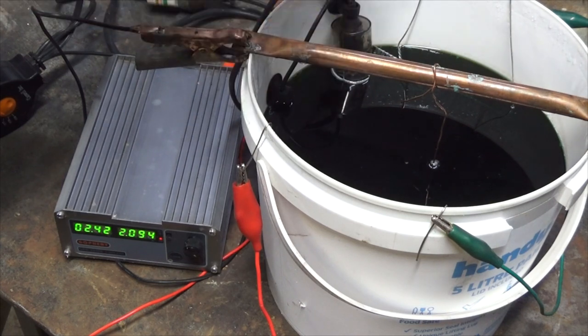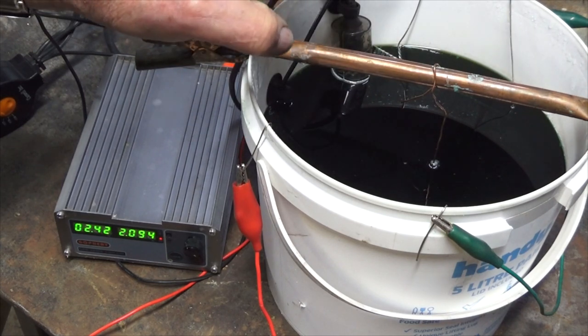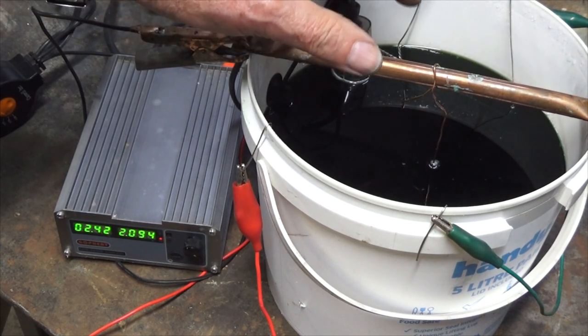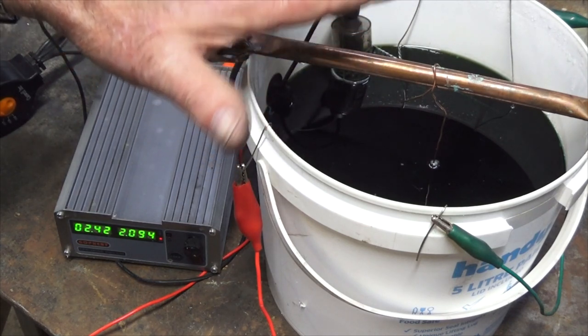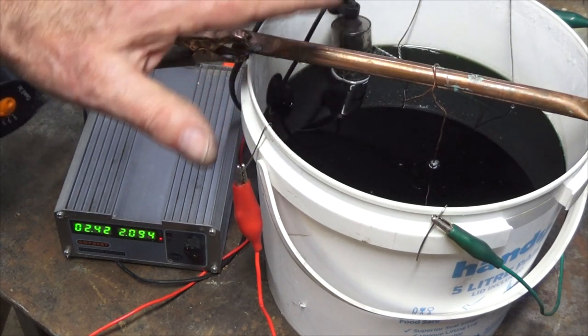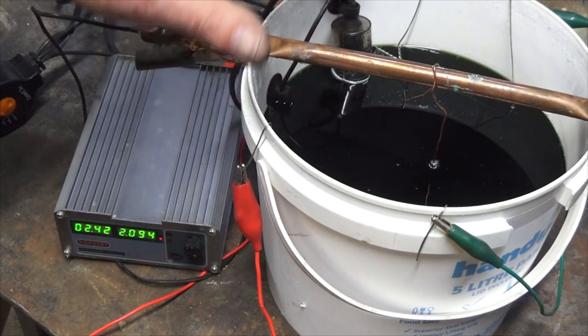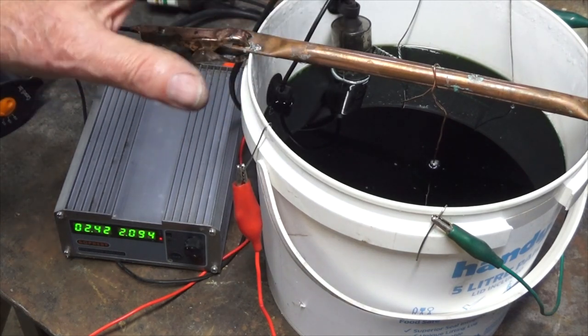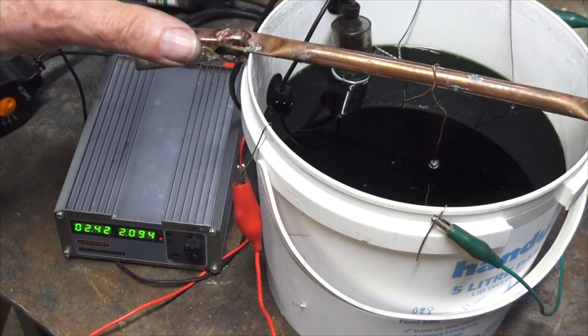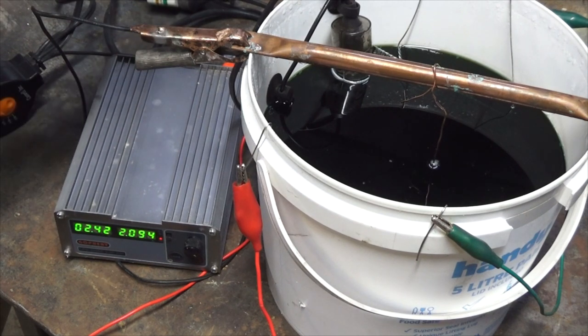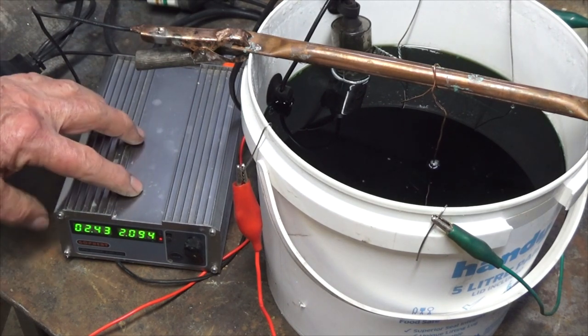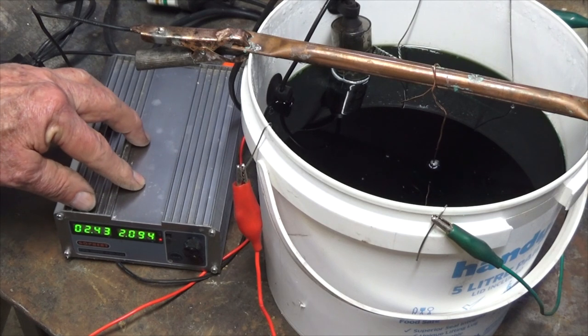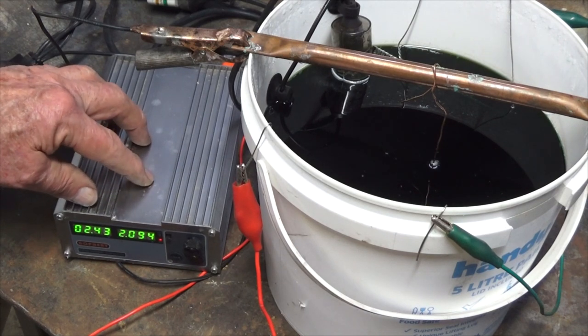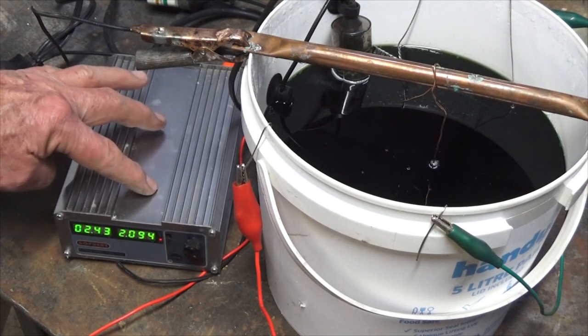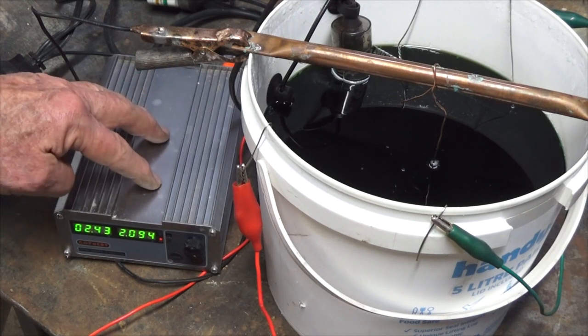If you do remove it from the bus bar and disconnect it electrically, then put it back in again, you can get two separate layers of electroplate on the surface, and that can lead to delamination later. So you just got to put it in and leave it, forget about it, come back in, you know, at the appropriate time and check it then. You can see from the power supply here we're taking 2.4 volts DC on that part, and it's running at the full 2 amps that I set the power supply to.